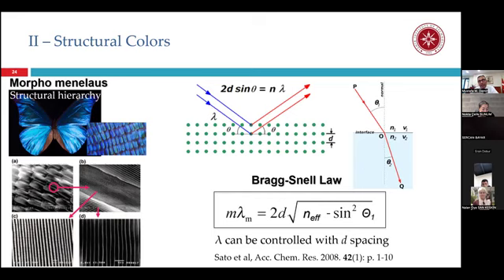The motivation is again coming from nature. You may know the Morpho menelaus butterfly. It has a very deep and attractive dark blue. If you are curious, when you look at the wing of this butterfly by microscopy, you see some periodic plates. If you increase the magnification slowly, at the very end you see uniaxially aligned protein fibers on the wing. They are equidistant, and the distance is around 150 to 200 nanometers.